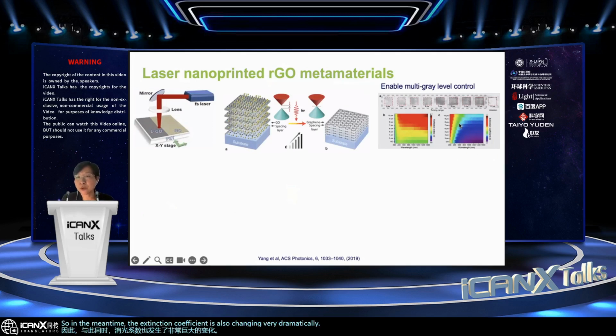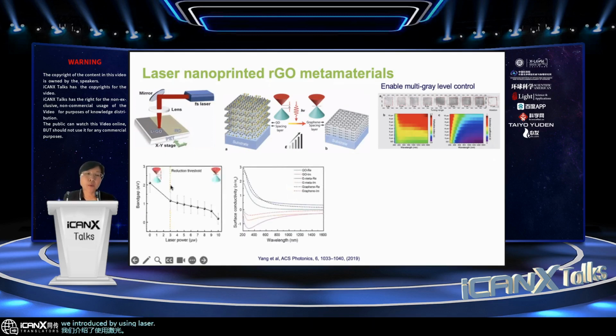So the change of this parameter means we're able to make lots of devices based on the contrast we introduced by using laser. When we measure the band gap, you will see that after laser reduction, the band gap of the material, graphene oxide, changed from 2.2 to about 0. That's almost fully reduced and then converted into graphene.